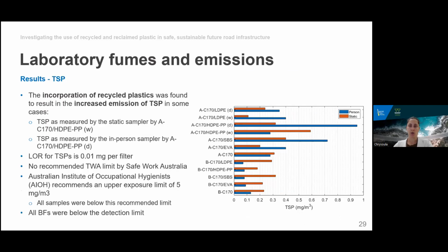All bitumen fumes were below the detection limit of 0.05 milligrams per filter. The incorporation of recycled plastics was found to result in the increased release of total suspended particles in some cases. Safe Work Australia has not set an upper limit for the total suspended particles. However, the Australian Institute of Occupational Hygienists recommends that workers are not exposed to more than 5 milligrams per cubic meter in a working day. For the graph to the right, it is evident that even at their highest concentration detected by the in-person sampler during the dry asphalt mixing of HDPE polypropylene, the measured emission was 19% of that limit.